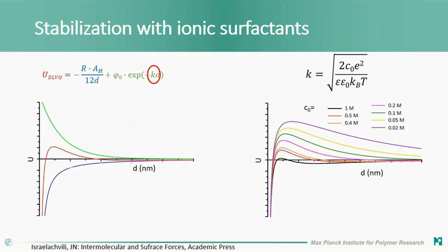electrostatic repulsion. As you increase, let's say, the salt concentration in the system, you could see at some point collapse of your system. It won't be colloidally stable anymore, just because you're screening the effect of the electrostatic potential of the surface. So it's something that is really important to control when you do mini-emulsion. It's how much salt. It's not just salt. Here it's the addition of sodium chloride, but it's also the pH of your solution. It's any charged species that you have in solution. It will strongly influence the stability of your emulsion, and it's something that needs to be controlled.